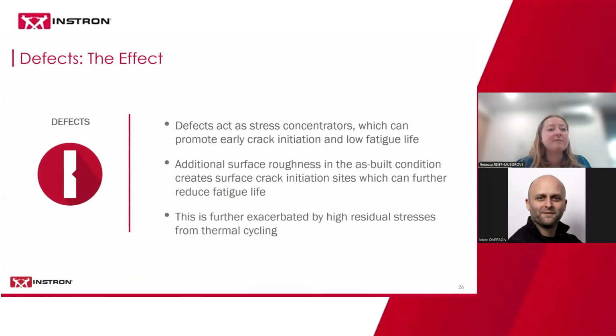Well, as you may remember from any material science class you may have taken, defects act as stress concentrators. So when you have a concentration of stress in one area, it can promote early crack initiation and therefore a lower fatigue life. Additionally, when we have high surface roughness, which we get in the as-built condition for additively manufactured parts, we also get surface crack initiation sites, which again further reduces the fatigue life if you start a surface crack that can run through the part.